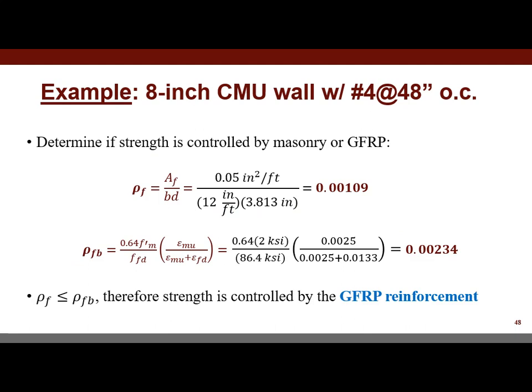Then I can determine what the reinforcement ratio is. If this was steel, it would just be A_s over b d. Here we have A_f representing the area of the fiber. And the importance of calculating the reinforcement ratio that you're using in your design versus the reinforcement ratio of the balance condition is it tells us where that tipping point is between tension controlled and compression controlled of the masonry, right? So if I know what the balance condition is, right in the middle between those two failure modes, if I'm less than that, I know the bar is going to rupture. If I'm higher than that, then the masonry is going to crush. And so it's important that we calculate our reinforcement ratio and our balance condition. And in this case, it's less than the balance. So it's on that left side of the plot that I showed you earlier. And so we see that we're going to get a GFRP reinforcement failure.